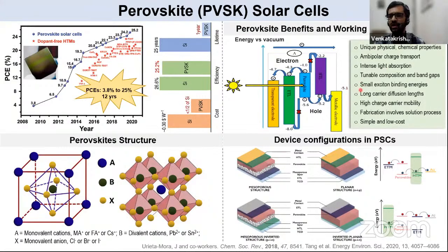And as I said, you can also tune its composition. Cations and the anions can be fine-tuned, and thereby you can also vary the absorption, and thereby you can also tune the band gaps. They have small exciton binding energies, which means you'll be able to split the holes and electrons quite faster. And they have a long carrier diffusion length also, and they have high charge carrier mobility, and the solution-wise process is what is often done for the fabrication of perovskite solar cells, which actually involves a simple technique and also a low-cost method.